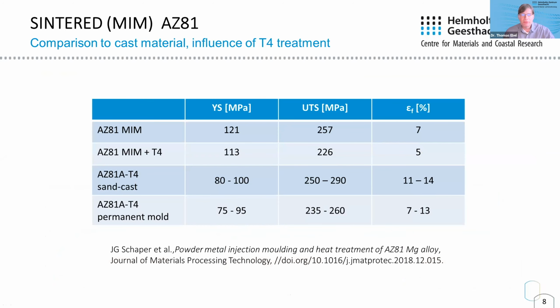We also processed an AZ alloy. It's an AZ81, and we looked also if we can see any influence of this T4 treatment, which is usually applied to these alloys. Again, we compared in this case with cast material from the literature values, and you can again see it's quite similar to the cast material. So I would say the properties are good, but they are not excellent, but they are really sound, and you can use this sintered material, and that's really a metal injection molded material.